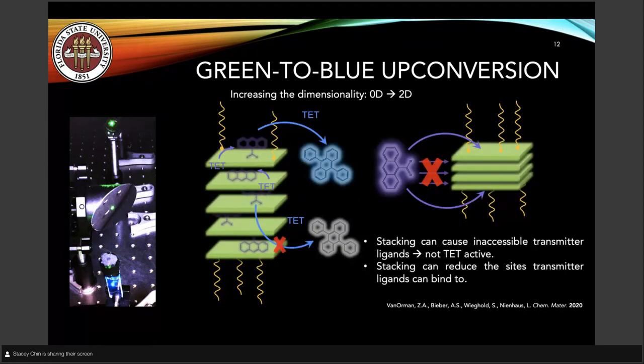You can either have stacking before you even try to add your transmitter ligand, which you can see here on the right. And with that, many sites where the transmitter ligand could bind are just inaccessible. On the left, you see stacking after exchange with the transmitter ligand. Then you can imagine that you have transmitter ligands that are buried in this stack and therefore are not TET active. So they just can't funnel their energy out to the upconverter itself.